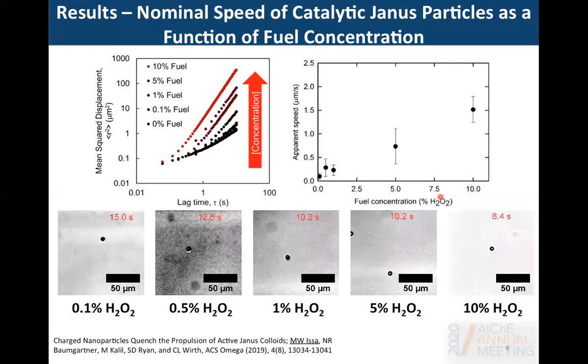As for the large error bars displayed, the origin of error has different sources, including particle fabrication and the nature of the experiments. For example, the platinum cap along the surface of polystyrene spheres may not necessarily cover 50% due to particles overlapping. Also, although we're working with a monodispersed suspension, variations in particle sizes are bound to be present, and that affects the propulsion speed as well.